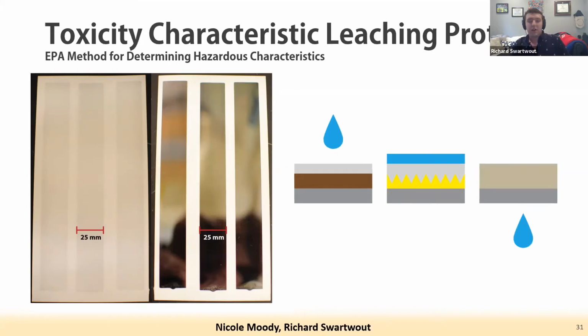With our method, we apply this backsheet, and under water ingress the perovskite is still destroyed, so you're not going to save your cell in that case anyway. But our backsheet chemically reacts and immobilizes the lead within the product. This is actually extremely effective.